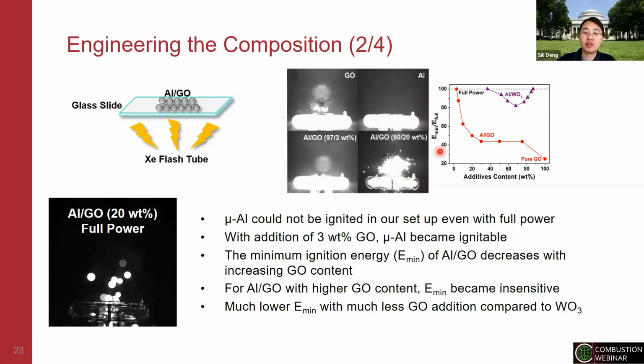And compared to what's being documented in the literature, the common additive of tungsten oxide, you can see with tungsten oxide, you first need to have a lot of additives. Second, you didn't enhance the ignition by a lot. But compared to that, with our GO additive, we can use only a little bit of GO to reduce the ignition energy needed by 20% or by 40% or so.